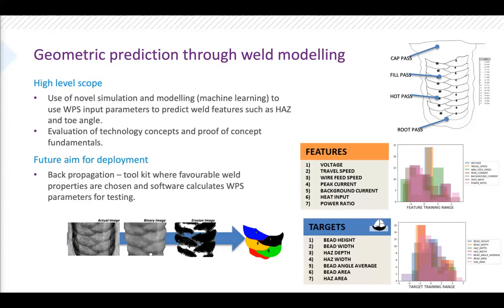So once you've got this established, the ultimate aim of this technology is to then select your desirable parameters, so toe angles that promote adhesion into the sidewall and to alleviate lack of sidewall fusion, or conditions to alleviate against wormholes. You select the desirable conditions that you want, and then the program will back propagate and give you a suite of welding parameters to test that will give you more favorable welding conditions.